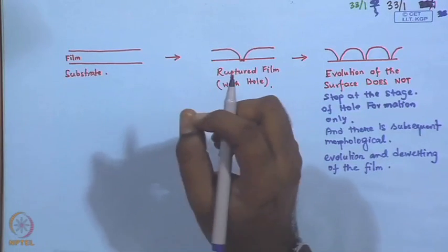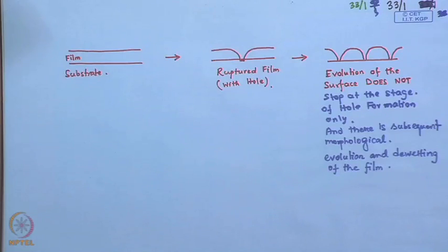Okay. So, there are essentially two aspects to thin film instability, or the spontaneous instability of a thin film. The first thing is that you initially start off with a continuous thin film which spontaneously ruptures, and the second aspect is that this ruptured film subsequently evolves. So, there is some additional reorganization within this ruptured film which eventually results in the final dewetted morphology. So, there are essentially two different parts of the whole process of instability and dewetting of a polymer thin film. If you look at the title of the module, I have deliberately kept it as instability and dewetting of the polymer thin film.